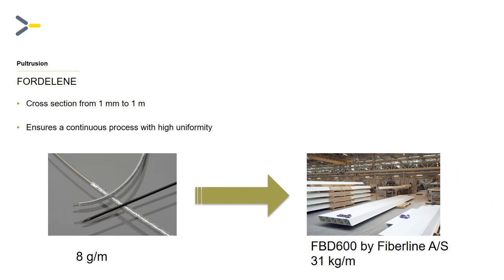Some of the benefits of pultruded cross sections: the cross section can reach from 1 millimeter to 1 meter in height. The image on the left shows a small tube which is used for brain surgeries, and this tube is actually below 1 millimeter in diameter, and it's pultruded as well with glass fibers. On the right, I have taken a picture of Fiberline's biggest pultruded cross section. This is a bridge cross section which measures 225 millimeters in height, and it's about 31 kilos per meter.